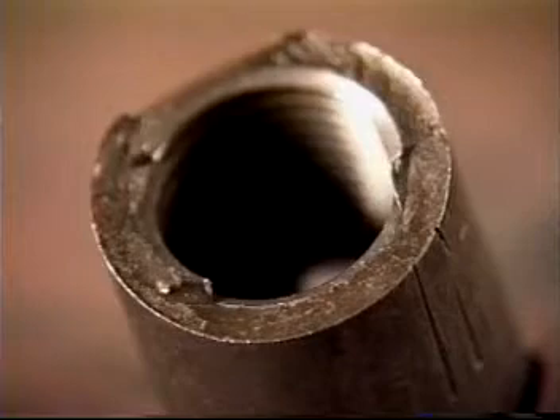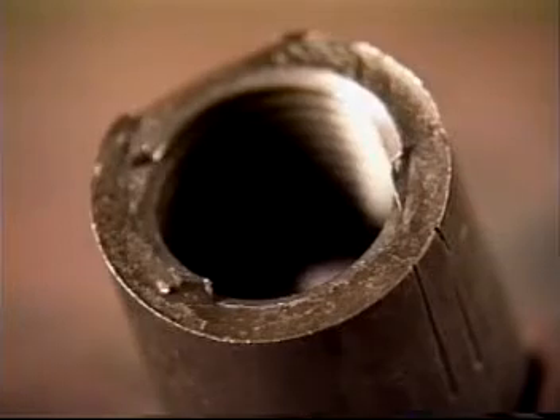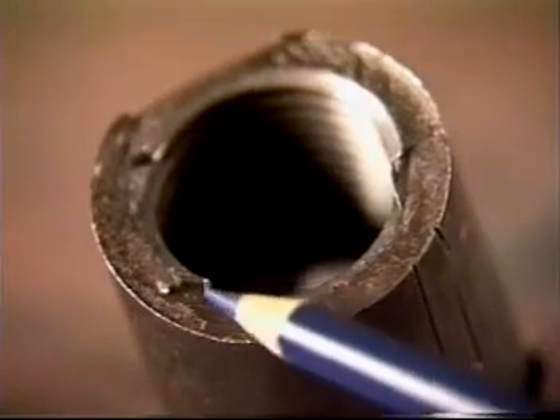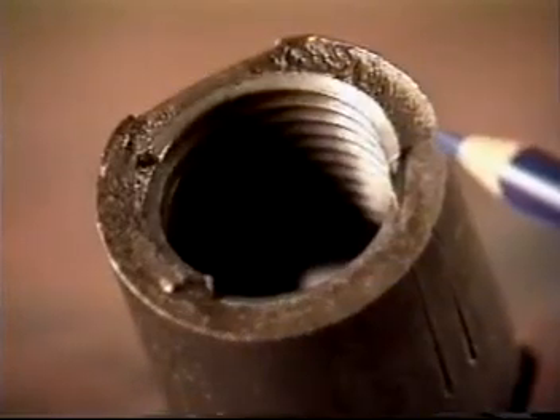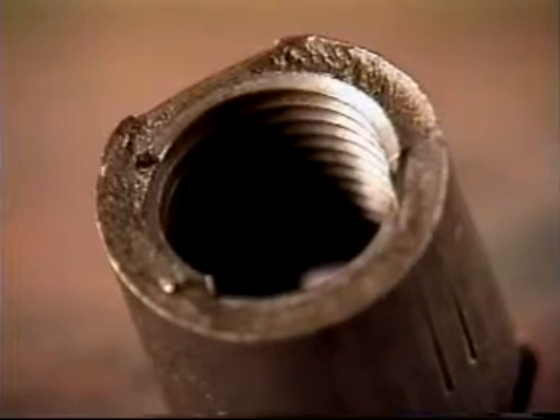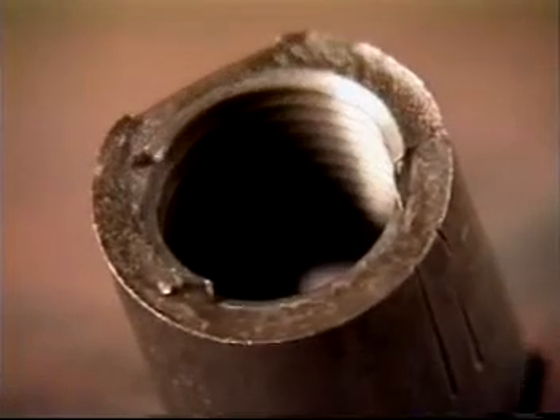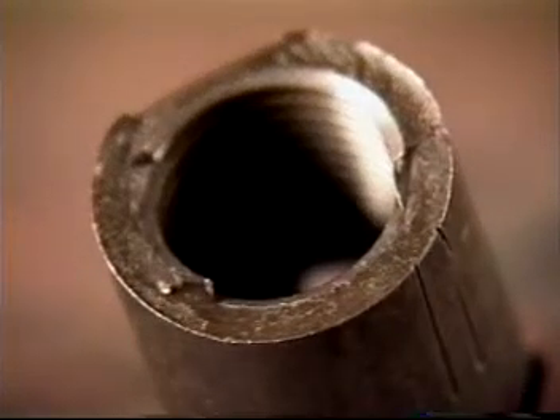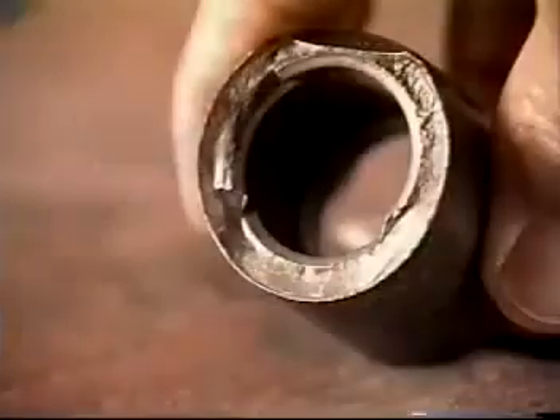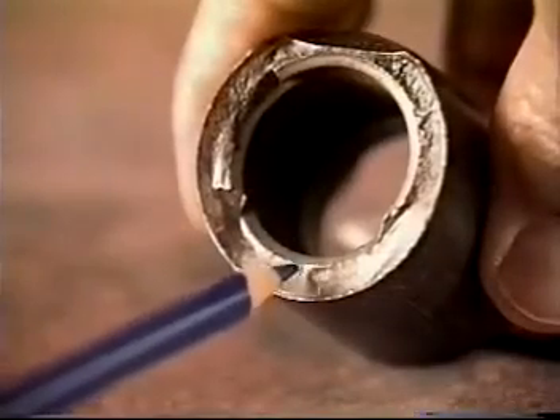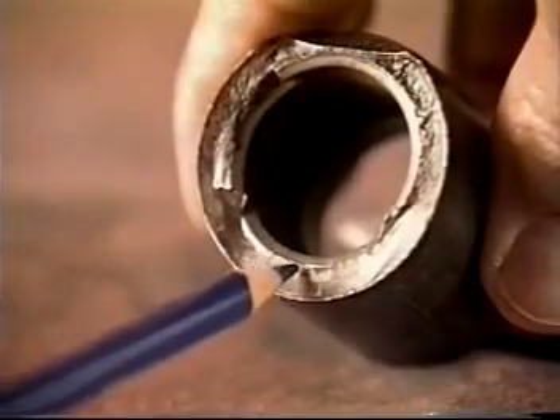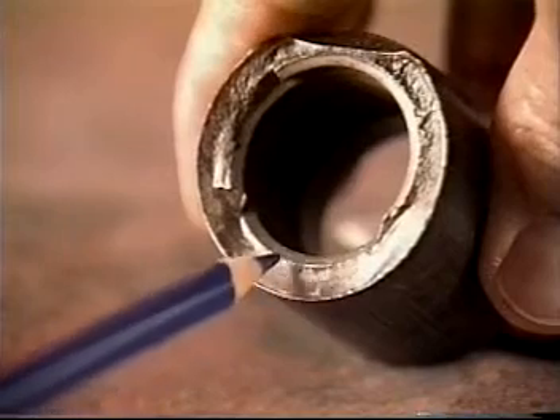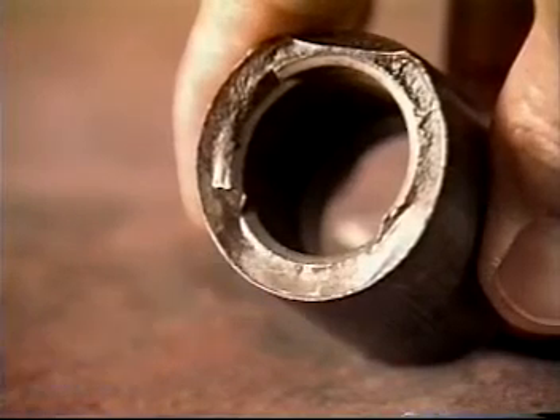Couplings which fail due to loss of displacement typically show a 1/3 to 2/3 failure. The shorter portion of the coupling will be approximately 1/3 of the length of the coupling. Notice that on the break face, the tensile tear is approximately 2/3 of the face, and the fatigue failure is the remaining 1/3. The ratchet marks will emanate from the thread root on the ID of the coupling. Ratchet marks on the OD indicate another type of failure.